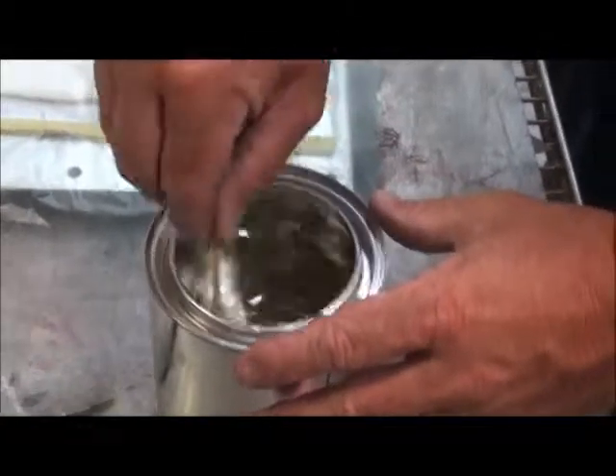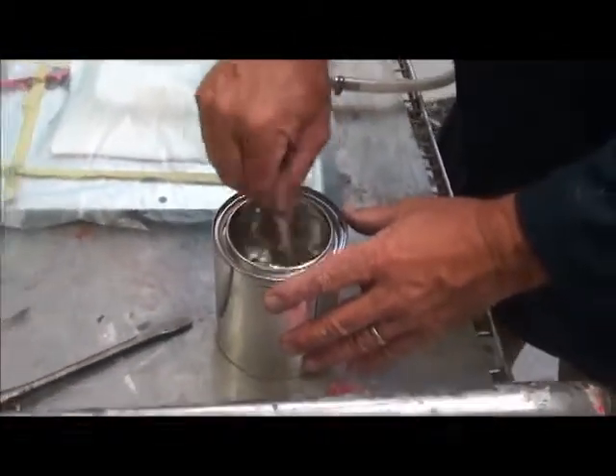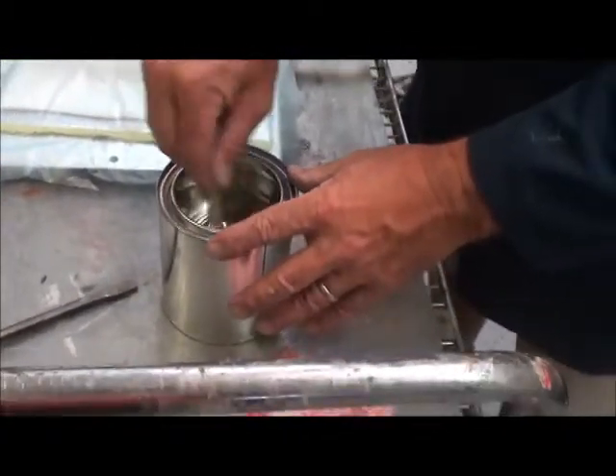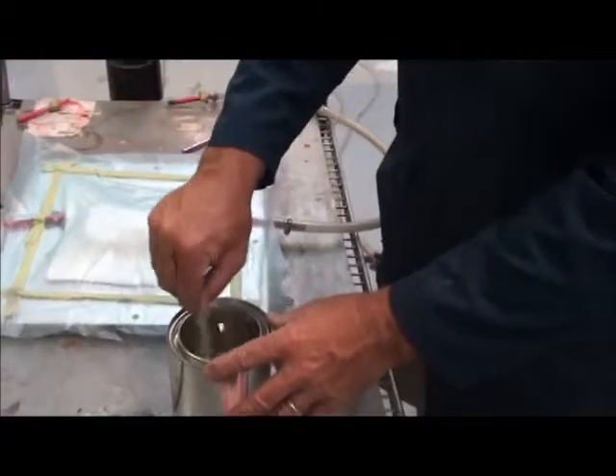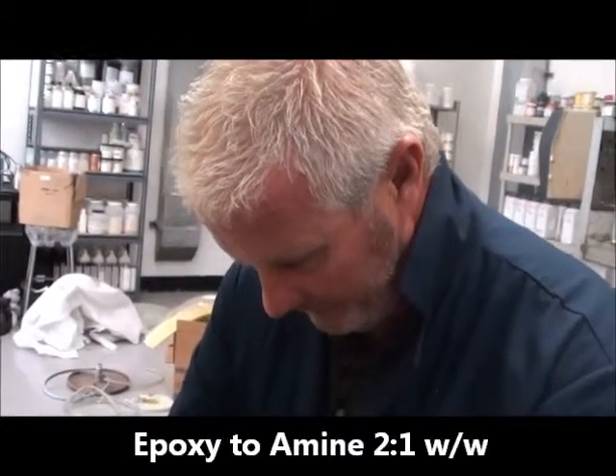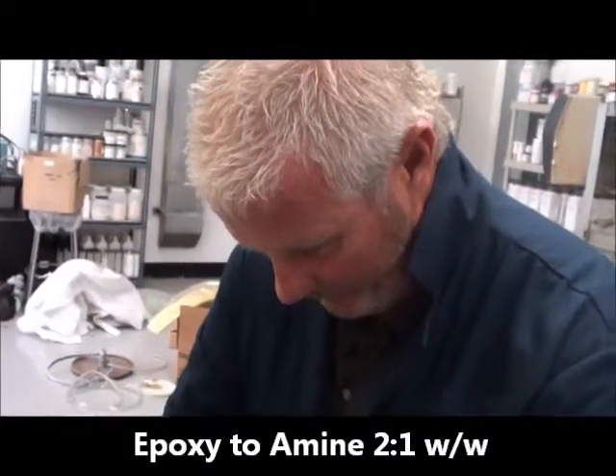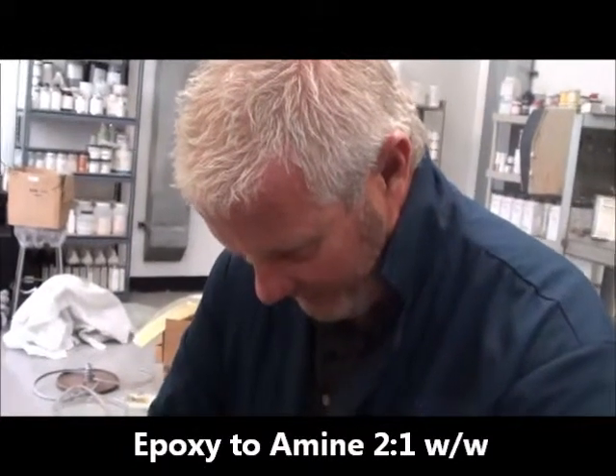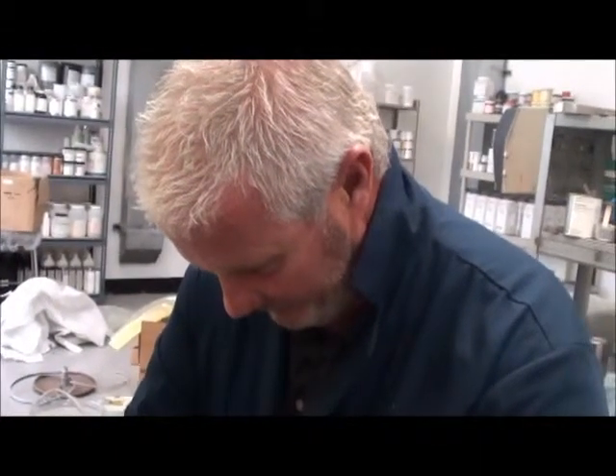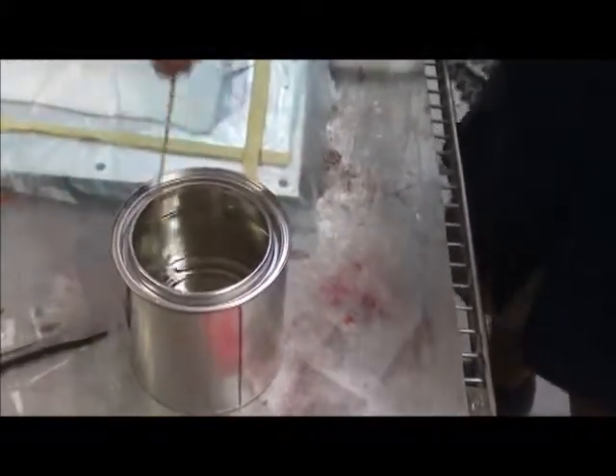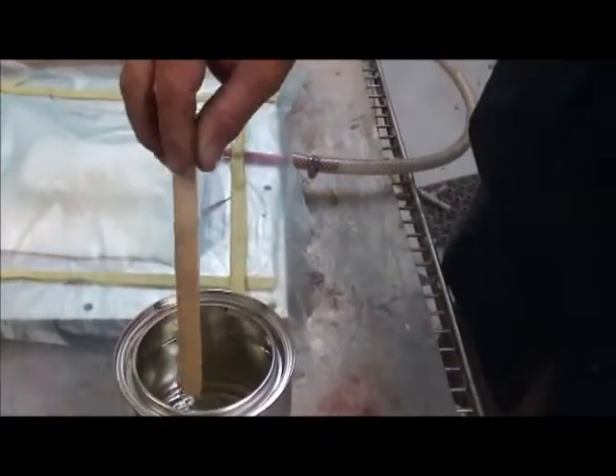This particular resin is mixed part A to part B. It's epoxy based, epoxy with cycloaliphatic amines and a reactive diluent. And it's mixed in the ratio of 2 parts to 1 part by weight. So we mix 500 grams of epoxy to 250 grams of the part B. And it has to be thin in order to flow through the hoses under vacuum infusion.